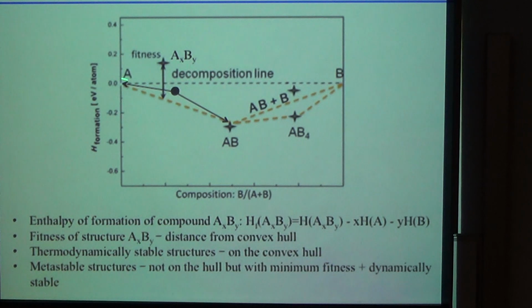So then we determine this convex hull for a given pressure, and this is how this convex hull evolves for each generation. Before this convex hull, I have to relax the structures within the generation. These points correspond to particular stoichiometry 1,1, this 1,4, and these are the thermodynamically stable compounds, right? So if you have a compound here, we call it metastable. We specify the metastability by the distance from the convex hull, how energetically it's above the convex hull.